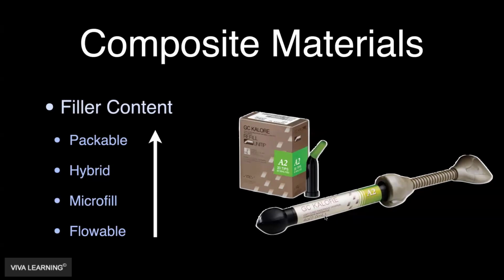So, we might use it almost as a liner underneath a direct composite. Obviously, those types of flowables could be used to repair the bubbles, the porosities that show up in your bisacryl provisionals. It had very limited usage. And then what we started to do is the manufacturers started to increase the filler percentage even in all of our materials that we called flowable. And so even in the group of flowable, you had very low viscosity flowables that had low to no filler. And then you had what we called high filler percentage flowables, which did still flow, but they had higher viscosity.